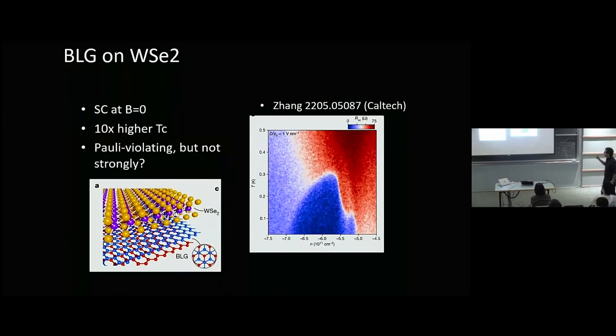Here, it's kind of spectacular, because Stevan Nadj-Perge's group at Caltech was actually the first to reproduce the superconductivity in Bernal bilayer, in kind of spectacular fashion. What they did is they put it on WSe2, because they like putting things on WSe2 for all these other reasons, and then they found that it's actually quite different. First of all, you do get superconductivity at zero magnetic field, and TC is 10 times higher, which is a very big effect. If you knew how to make TC 10 times higher in any other material, you'd be very happy, right? So we were very happy when we saw this. And they saw that it's different. It's Pauli violating, but maybe not nearly as strongly. So that's sort of what I'll talk about.